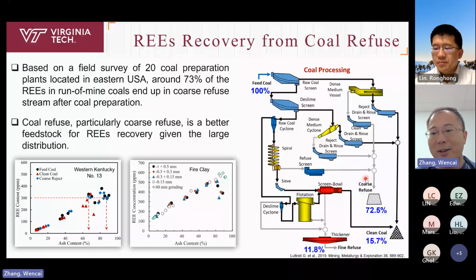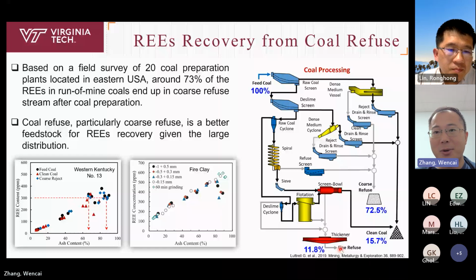And only 15.7% of rare earths in the feed goes to the clean coal, and 11.8% of rare earths in the feed goes to the fine refuse. So this is interesting, okay? It tells you that if you want to recover rare earths from coal, you need to go to the coal refuse, because over 70% of rare earths in the feed goes to the coal refuse. So this is the reason why at the beginning we focused on rare earth recovery from the coal refuse.